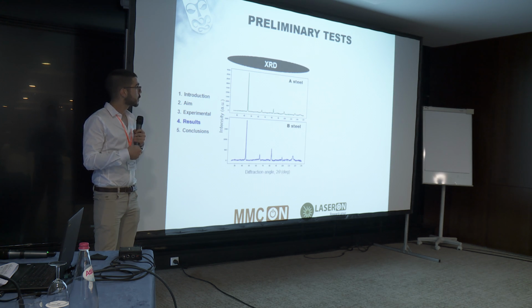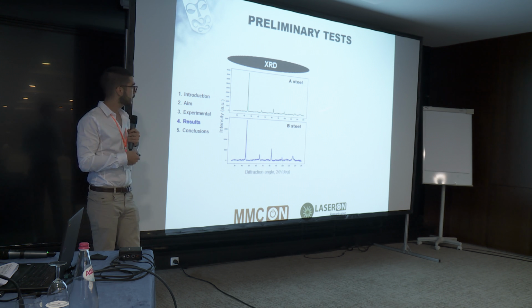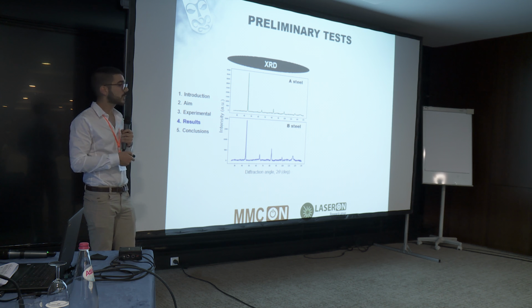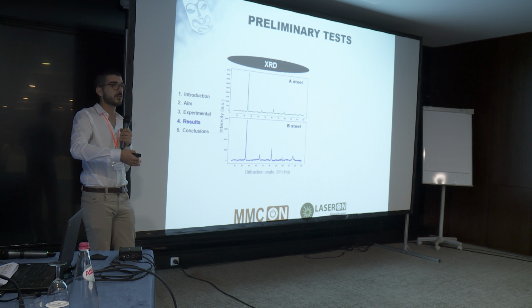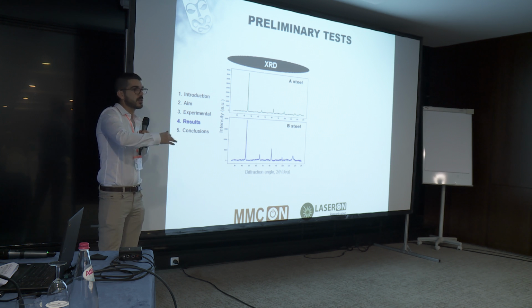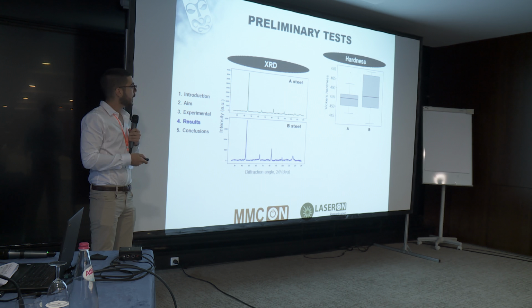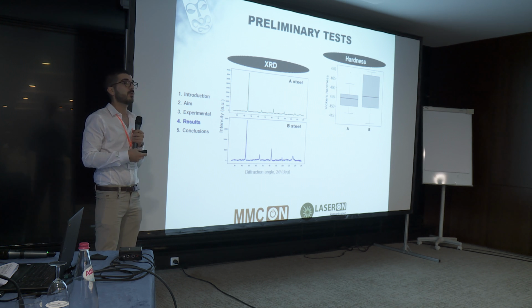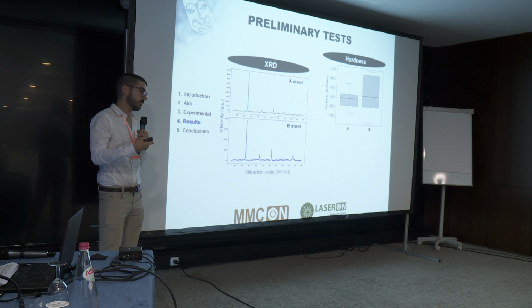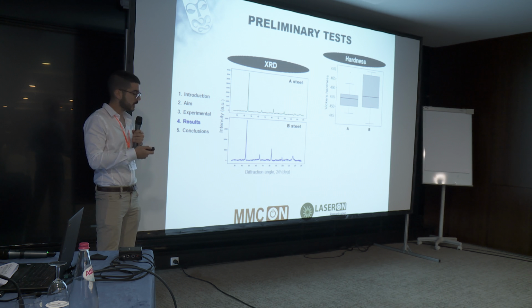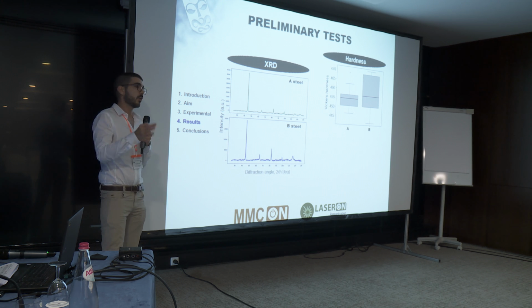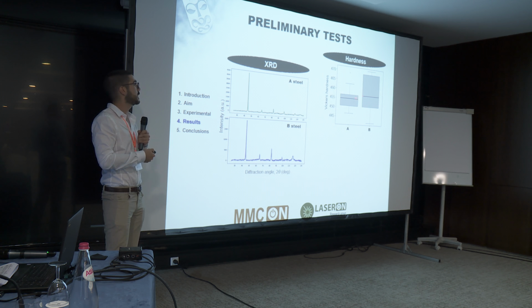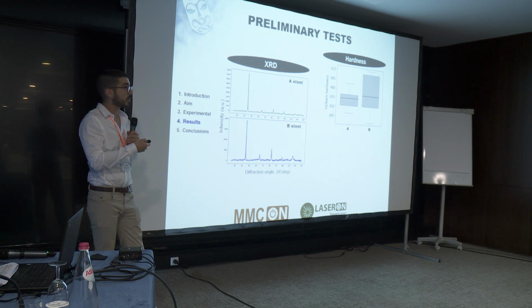So now the results that we got. First we did some preliminary tests. We took a few samples to X-ray diffraction analysis just to be sure that we were dealing with the same microstructure, which corresponds to a martensitic microstructure characteristic for quenched and tempered steels. Then we also measured the hardness just to ensure that we were fulfilling the heat treatment specifications of the specimen hardness, and we can see that not only were they both significantly alike, but we also got the 46 Rockwell C, even though here is a Vickers measurement, which corresponds to 460 Vickers.